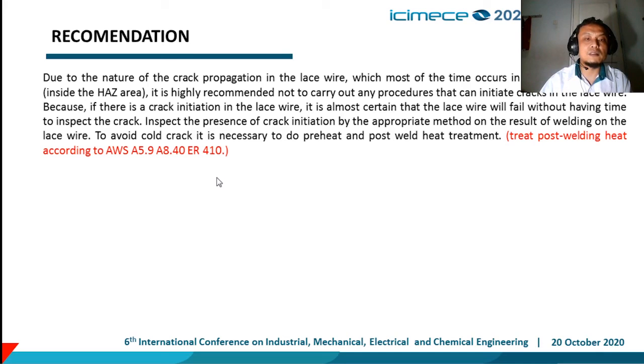Inspect for the presence of crack initiation by an appropriate method on the result of welding on the lace wire. To avoid cold crack, it is necessary to do preheat and post-weld treatment according to the AWS standard.